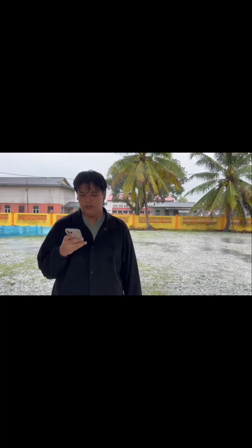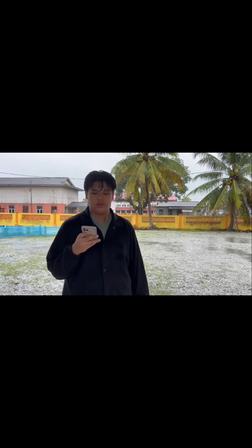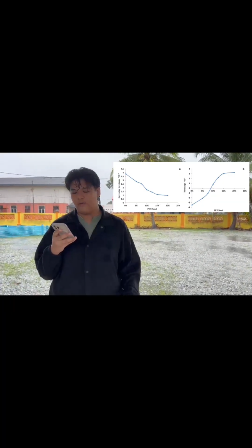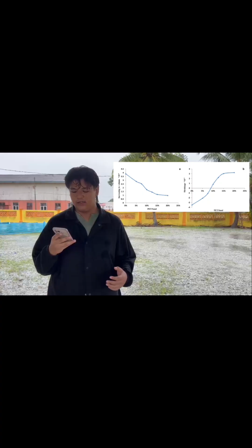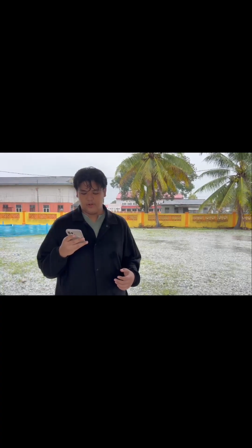Dry density measurement was performed to observe the weight reduction caused by the lightweight PET particles. A shrinkage and expansion test was conducted over 140 days to monitor volumetric change during wetting and drying. The absorption test measures the rate at which hardened concrete absorbs water.